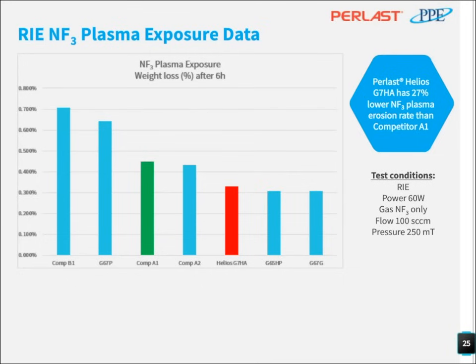So let's start with NF3 plasma. We exposed all these rings, you can see, to NF3 plasma in an RIE tool, reactive ion etcher tool, for 6 hours. As you may know, NF3 is one of the most aggressive gases used very commonly in cleaning. Therefore, resistance to NF3 is very critical for an elastomer seal.